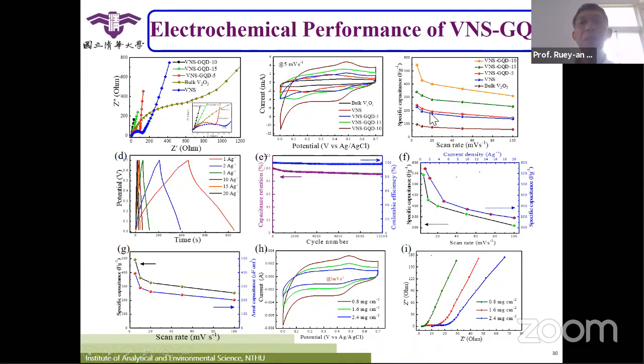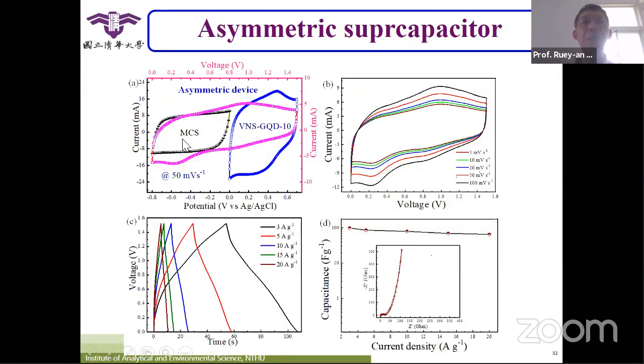So from the anodes, their value will be around 550. From the cathodes, the capacitance will be around 550. So that means this value will be quite close. And then when you merge them together, they can have very good efficiency here. So that's when you use the MCS as the negative electrode here.